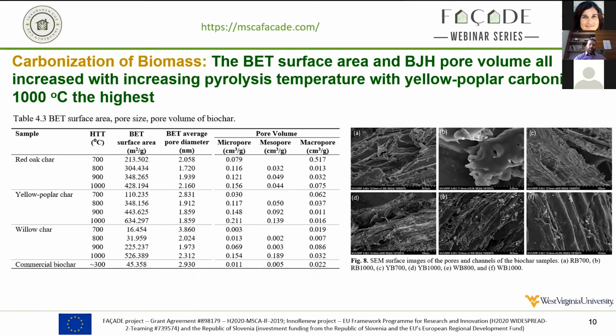Another property that's important is BET surface area, especially in terms of using this for soil amendments, but also using it for supercapacitors or for electronic type purposes. In here, you can see that there are differences in pore sizes, which become important later too. But you can see as you heat this to a higher level, you get more surface area. So you're taking out more of the cellulose, hemicellulose, lignin structure. Especially at these higher temperatures, you're taking out more of the lignin structure and turning that into carbon because everything else is pretty much gone. And you're starting to get higher surface areas and you're producing more porous structure.